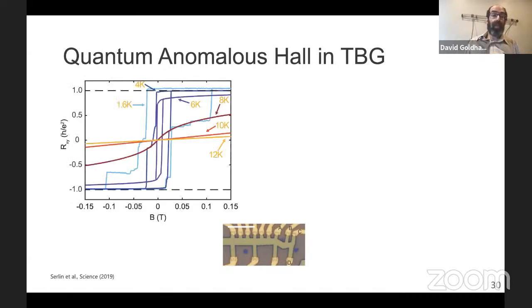Now we had surmised that this was likely a Chern insulator, but we didn't have quantization. And Andrea Young and his group searched their library of samples and found one that had alignment with boron nitride. And in one part of that sample, they were able to make measurements where they could actually see quantized resistance, showing that this indeed was a Chern insulator, a quantum anomalous Hall system, which is quite amazing, that this just jumps out of this structure without any magnetic doping.